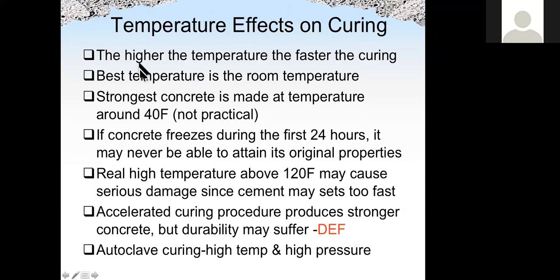So to summarize, the effect of temperature on curing: the higher the temperature, the faster the curing, and the best temperature is the room temperature. So that's very convenient. The strongest concrete is made at temperature just above freezing temperature, around 40 degrees Fahrenheit. But that is not very practical in most cases.